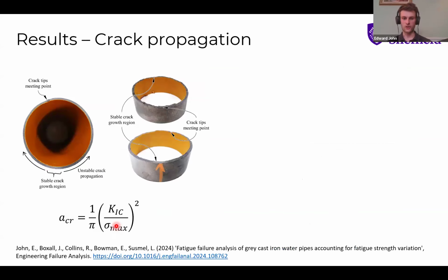So moving now from that, that was all looking at predicting when a leak will begin. Looking a bit now at what we found once a leak is formed and how it behaves, how it grows. So these show some fracture surfaces from uniaxial tests. So these were tension compression tests. And what we noticed when we looked at the fracture surfaces is that they all showed a fairly clear, stable crack growth region. So this was a bit like the PVC pipe that Kobus showed us earlier, where you have this area of the crack gradually growing until it gets too big and then is able to, in one load cycle, propagate all the way around the pipe.